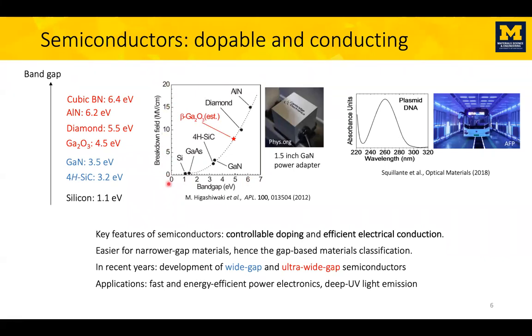And this relationship is not just super linear. It's either the square or the cube power that you see here from this empirical law. So going from silicon to gallium nitride, you have an order of magnitude at least boost in the breakdown field, meaning you have much higher voltages. And you can do things like this. This is like a power adapter, like a computer adapter made with gallium nitride, except instead of being a big brick that we're used to seeing on computers, it is shrunk down to 1.5 inch.